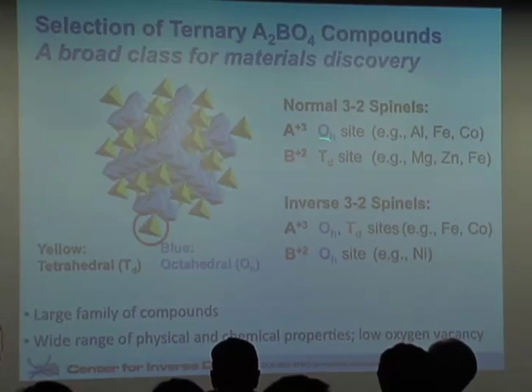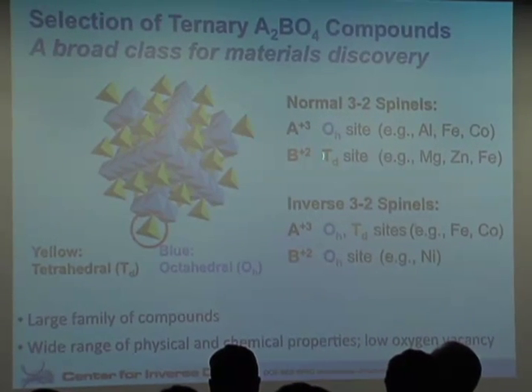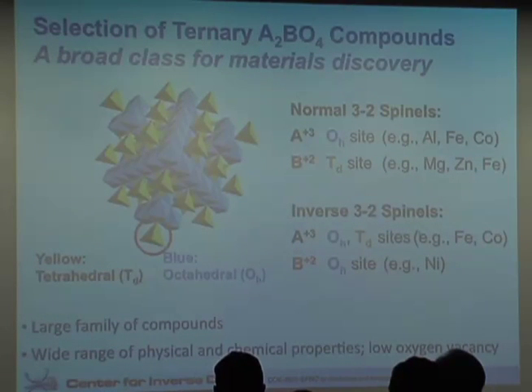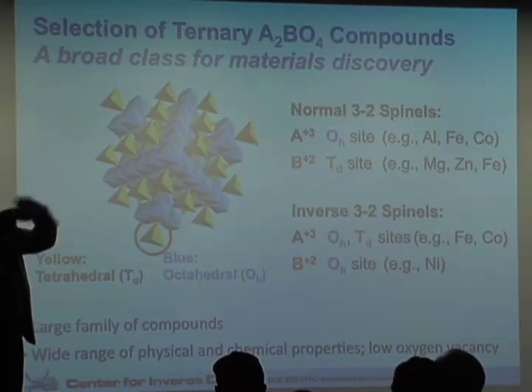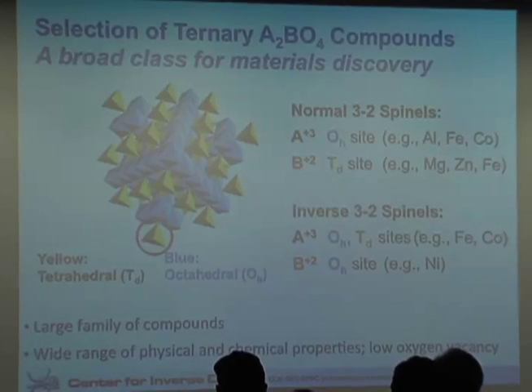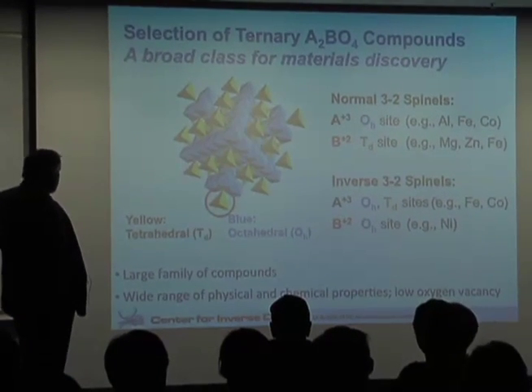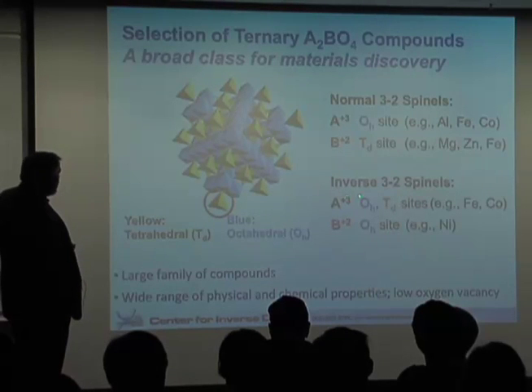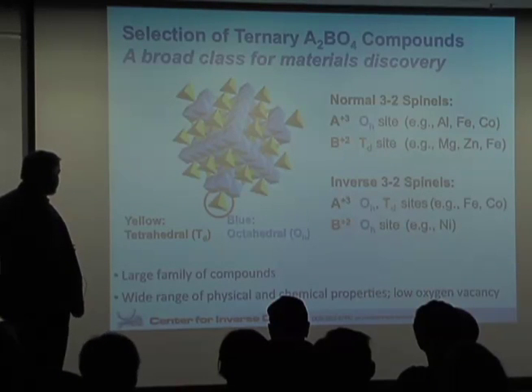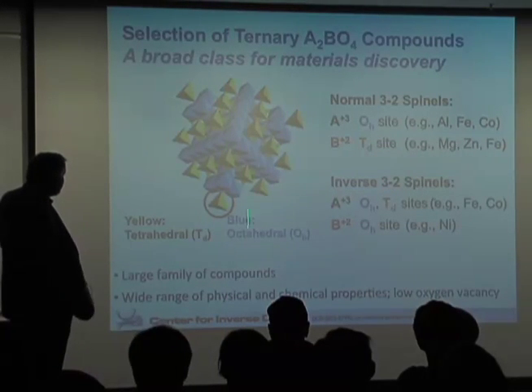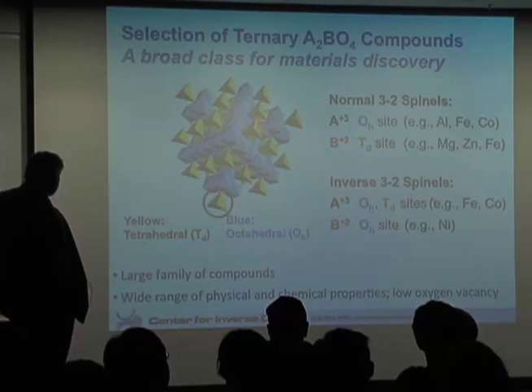These spinel systems are pretty interesting. They have a 3+ cation that sits on octahedral sites, and they have a 2+ cation that sits on tetrahedral sites. And actually you get anti-site defects when those switch. And that turns out to be one of the fundamental doping mechanisms in these systems. And in fact, there are spinel systems that actually are inverse spinels, where the 3+ cation goes both to the octahedral site and to the tetrahedral site, and the 2+ cation actually also goes to the octahedral site. And you can actually imagine that might allow you some additional doping and conduction mechanisms.